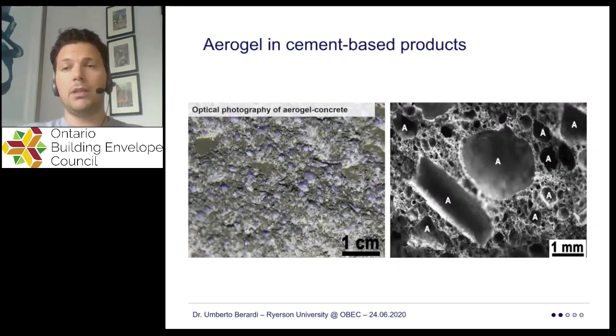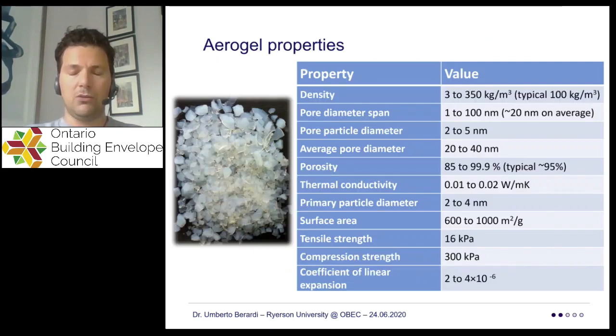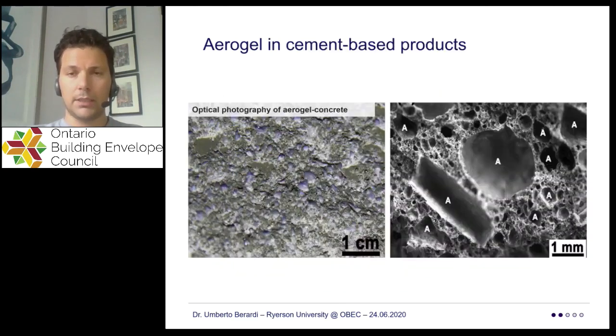Now, if you take this aerogel, and I showed you previously some particles of aerogel, you can put these aerogel granules in any material that we typically use in building construction. You can put them in cement-based mortar or concrete. It's not necessarily an easy approach, because you are using a material that still has a quite high cost in a material that generally has a low cost, and you are putting a super insulating material into concrete, which is not known for having a very low thermal conductivity. But it is a good option, imagining that in the years to come we can start having concretes that also have a low thermal conductivity.